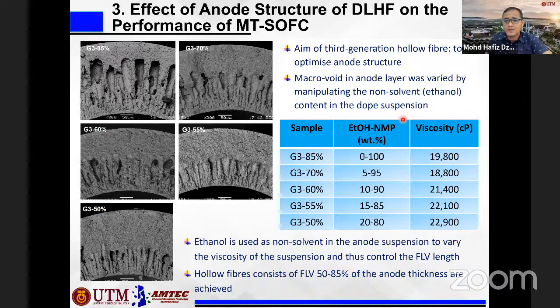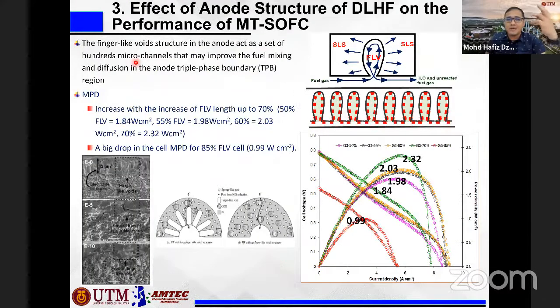Therefore, when you increase the ethanol content in the dope suspension, you produce a shorter finger-like structure compared to when you put in a lower amount. The finger-like structures in the anode act as hundreds of microchannels, and therefore can improve fuel mixing and diffusion in the anode triple phase boundary. Triple phase boundary means the location where the fuel, the oxygen, and the electron can travel and transfer to each other. So if you have a higher triple phase boundary, it is more likely that higher power will be generated.